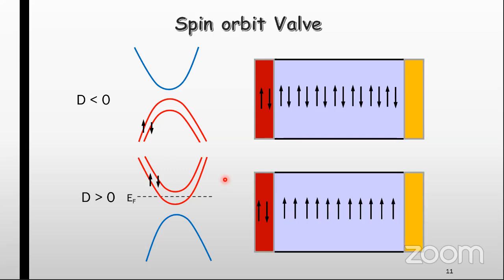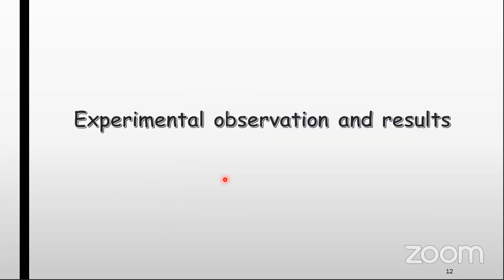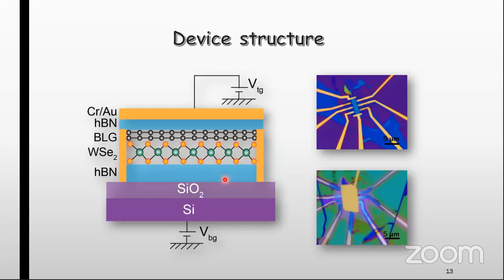Okay, so now we will be discussing our experimental results and observations. This is our device heterostructure, where we have put a top gate and back gate. The main purpose of having a top gate and back gate was that we can independently tune the charge carrier density and displacement field in our system. This is the device image without the top gate, and this is after fabricating the top gate.